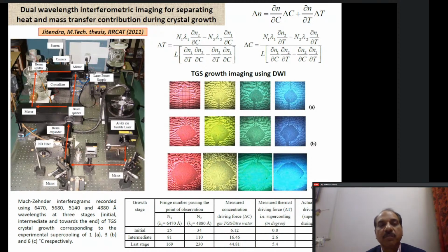So these are two coupled fields, right? Temperature as well as concentration. Both of these fields depend on each other. If you increase the temperature, concentration decreases. If you decrease the temperature, concentration increases. So these are inversely related and they are coupled. But usually we neglect the effect of temperature, because we say that we have reduced the temperature by either 1 or 2 degrees, and whatever is happening is only because of the concentration fields.